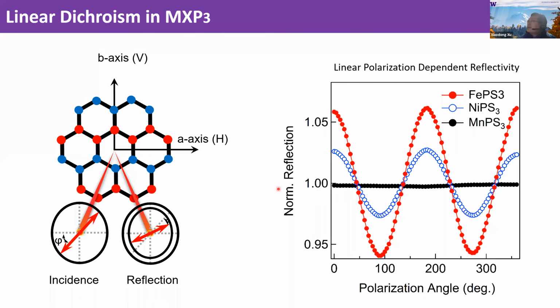And here's the data. We measure this linear dichroism from 3 different crystals: iron phosphorus trisulfide, nickel phosphorus trisulfide in blue, and the black dots represent manganese phosphorus trisulfide. So basically, we measure normalized reflectivity as a function of the incident polarization angle. And clearly, the data shows that both iron phosphorus trisulfide and nickel phosphorus trisulfide have strong optical anisotropies. But the manganese one doesn't show any optical anisotropy, doesn't show linear dichroism.